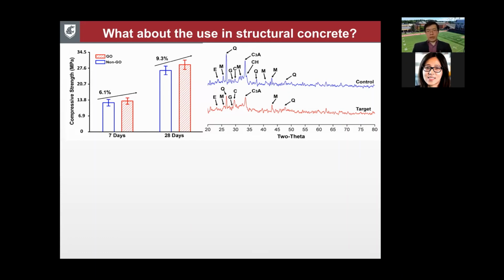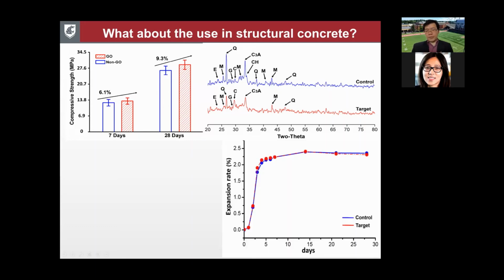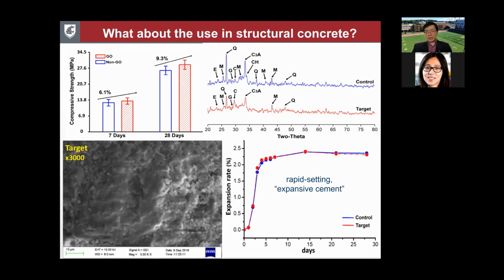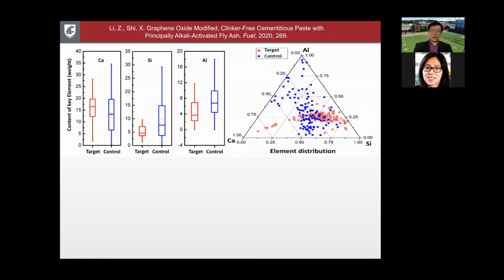One application we're exploring right now is tube concrete. So with FRP tube, fiber reinforced polymer composite as the tube material, and inside you basically have this concrete. And we designed the binder to be an alternative or green alternative to expansive cement. And it's rapid setting, and hydration products are quite refined. So there's very little porosity. So that's a pretty good alternative to expansive cement. Now, again, we use the same tools to understand the hydration products and how the graphene oxide, even though it's used at a trace amount, 0.02% by weight of fly ash, significantly changes the hydration chemistry and the final products.